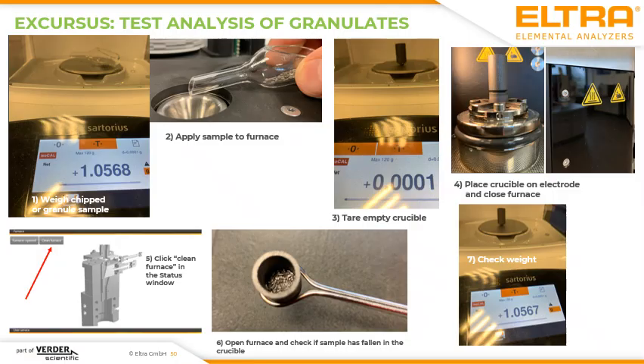When you have an unknown sample in a granule shape, first weigh the sample on the balance and apply it to the furnace. Then you go to the balance again and weigh a new graphite crucible. Tare this weight, apply the crucible to the sample port and close the furnace. And then it's possible to go to the furnace manual and click on Clean Furnace. This means that the slider opens and all the granule sample which was applied to the furnace will now fall down into the crucible.